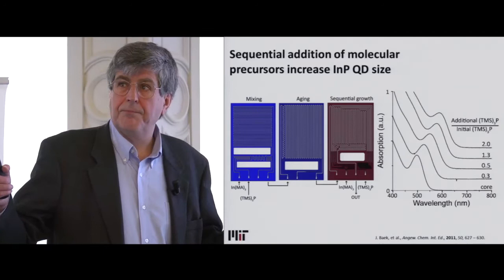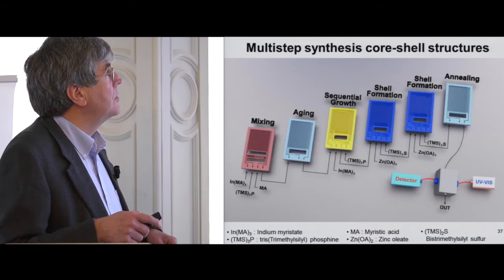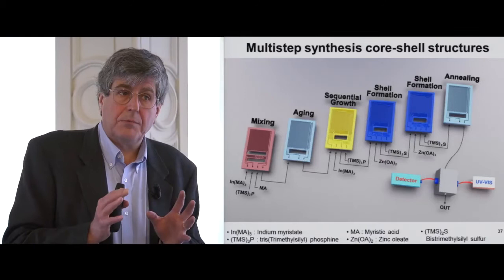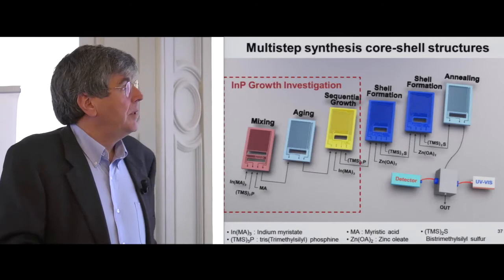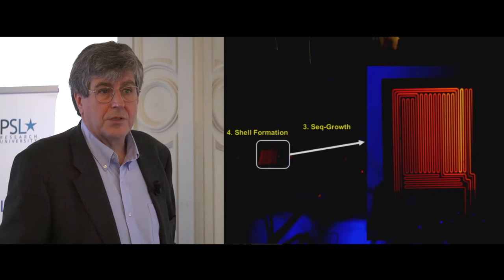We can then do multi-step synthesis using core-shell structures. In order to get good quantum emission out of these systems, you have to cover the core with another material with a higher band gap. We cover it with zinc sulfide. We grow the indium phosphide, put a shell on that, anneal it, and have online measurements of what happens in the system. Here's a picture of what happens when you see it in the dark and put UV illumination on it — as we finally grow the shell, you get larger and larger luminescence from it.